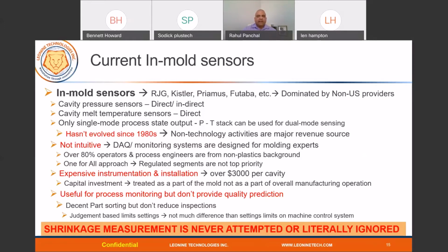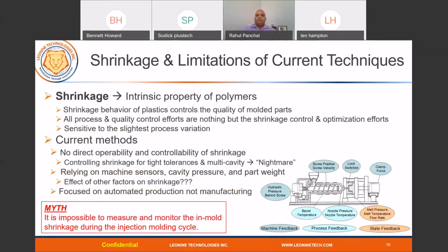You can achieve the quality prediction by measuring the shrinkage, which is possible, but that shrinkage measurement is always literally ignored, thinking that there's no way you can measure the in-mold shrinkage during the molding cycle. And that's why it has never been attempted. Why is the shrinkage measurement important? Because it's the intrinsic property of the polymer, shrinkage behavior controls the quality of the molded part, whether it's the aesthetic or the dimension.